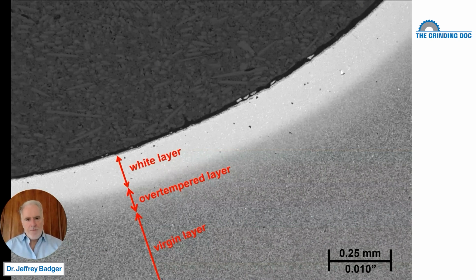You grind the workpiece, and when you grind that workpiece at the top surface, at the ground surface, if the temperature got high enough to cause a recrystallization of, let's go with steel. Nickel alloys also experience this, but we're going to go with steel. If the temperature got high enough to cause the tempered martensite to transform past the austenitizing temperature and then form untempered martensite, what's happened is the top surface has recrystallized. It hasn't melted. Steel did not melt, but the very top ground surface recrystallized.